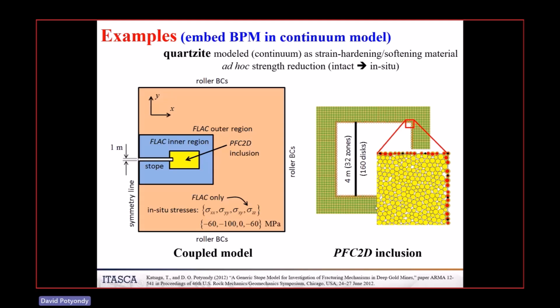And this is this coupling scheme whereby we basically create a bonded system in this region of space. We then identify the boundary particles, and then we map each boundary particle into the edge of an element. And then the forces acting on these boundary particles get sent as traction boundaries to the continuum grid. And meanwhile, the deformation of the edges of these zones is imposed by these boundary particles.